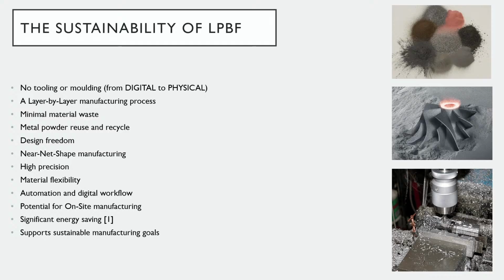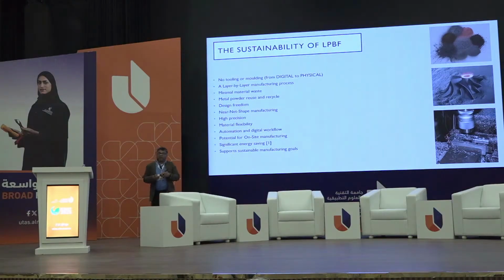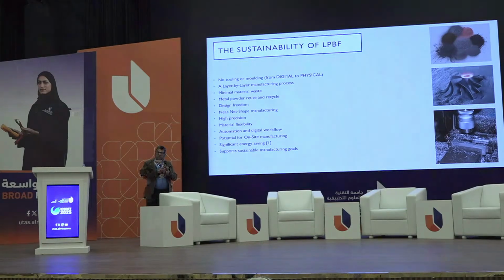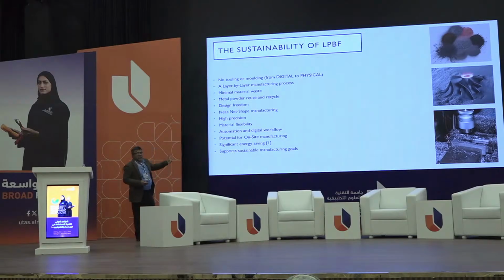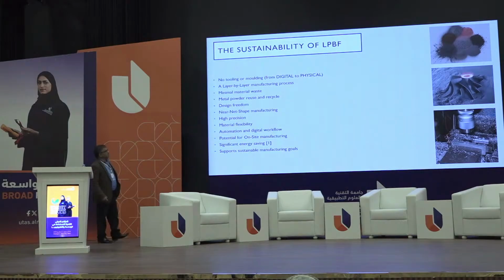Significant energy saving. You know, most laser systems are plugged to the wall, but the output energy is way lower. A 1 kilowatt fiber laser, like the laser we use in our machine, is only 200 watt. Some machines have 1 kilowatt, and this can bite and melt any metallic or ceramic material. And the last point here, this is very useful in repair of material. Like I saw a factory in Ireland for Lufthansa, they repair the damaged turbine blades. So whatever the wear is, they machine it, achieve a flat surface, and then they rebuild on top of it. So it can be used in repairing damaged parts.